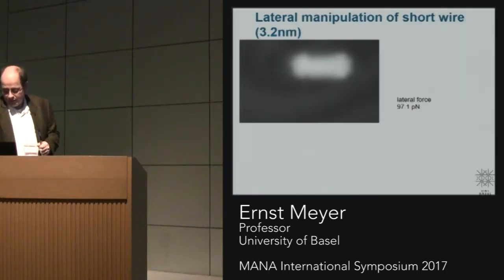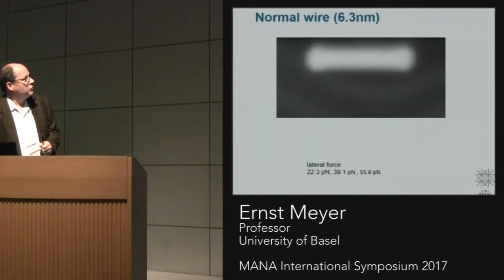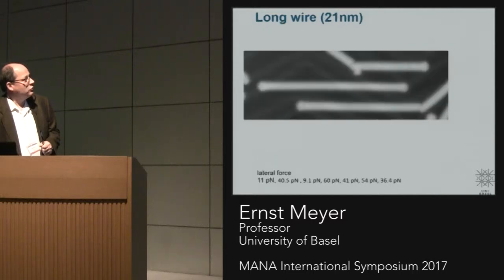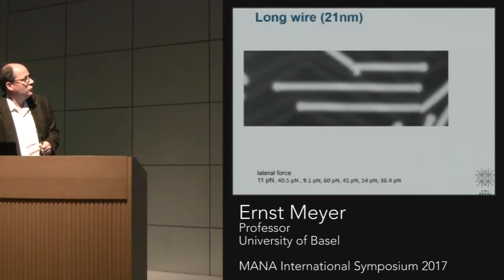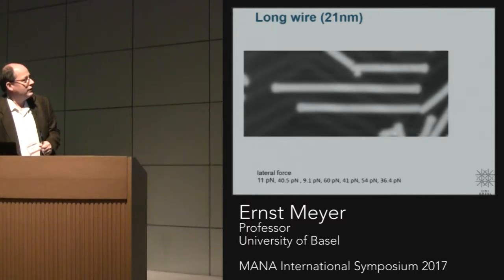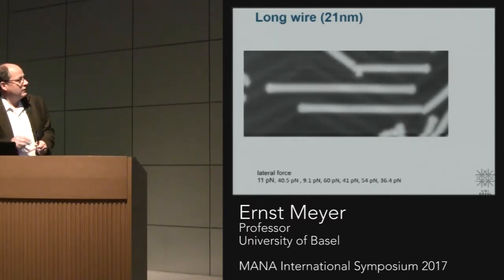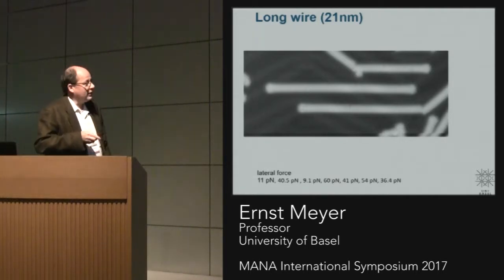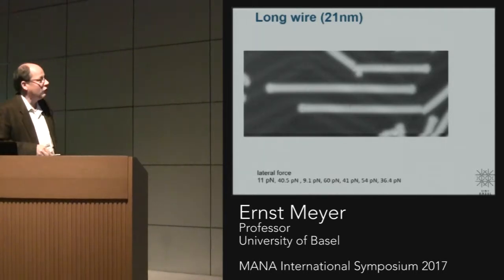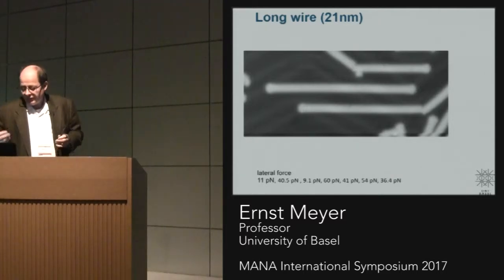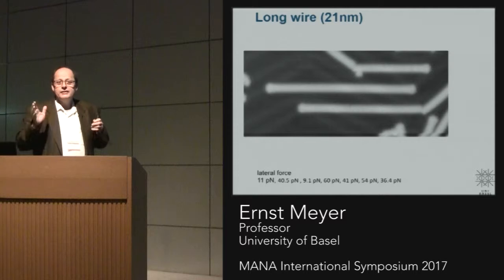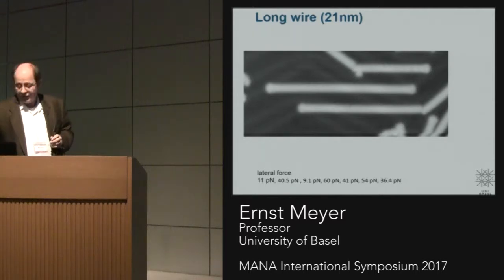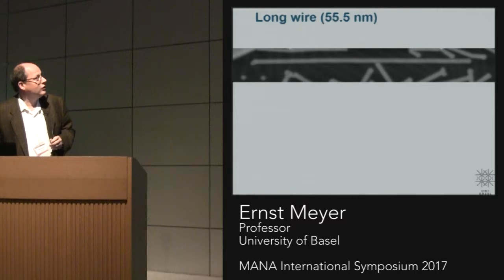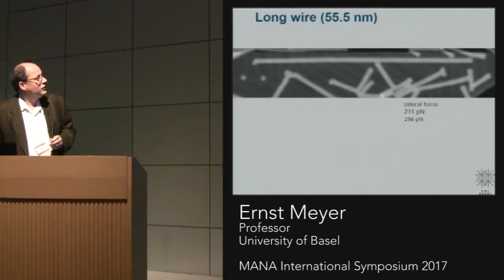So the first series here shows lateral manipulation. So this is a short wire, and you see you can move it around. This is a little bit longer, and you see also it's possible to move. Now 21 nanometer, you see it moves actually more or less also very easily. The forces are always around here a few piconewtons, so actually quite small, and they don't really scale with the length. So there is quite some variation, but you cannot tell that a longer wire would need much more. So this is a very long wire, so 55 nanometer.